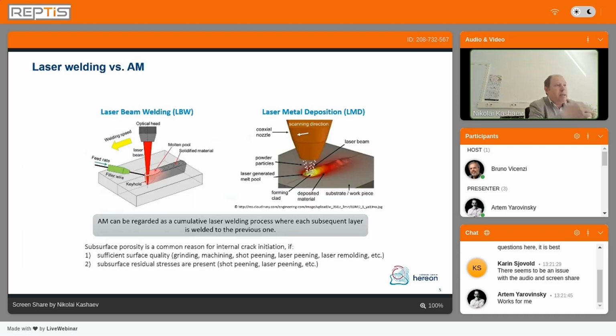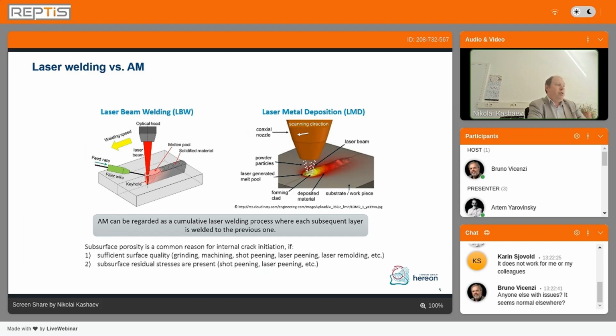And our study is based, for example, on the laser processes, because laser processes can also be considered important additive manufacturing technologies. And in principle, there are a number of similarities if we consider just laser beam welding or laser beam additive manufacturing. In principle, additive manufacturing can be regarded as a cumulative laser welding process where each subsequent layer is welded to the previous one. And here also subsurface porosity is a common reason for internal crack initiation if sufficient surface quality, grinding, machining, shot peening, or laser peening, laser remelting is applied. And subsurface residual stresses are present if we introduce shot peening or laser peening.